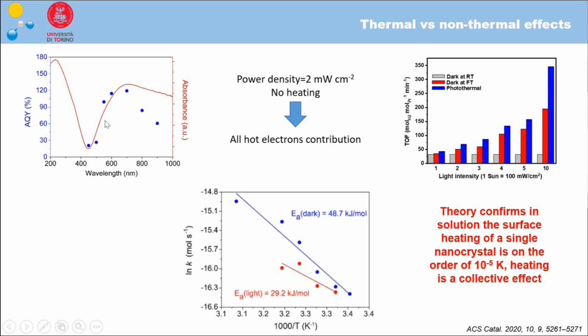You can see that we have an apparent quantum yield which is above 100%. So this, if you are familiar with photocatalysis, can be quite a strange result. Usually when you use a semiconductor, you can have a maximum of 100% quantum yield, because with one photon you generate one electron and one hole. However, there are some semiconductors which can produce more than one carrier per photon. And in the case of plasmonic materials, we have to remember that with one photon we excite a collective motion of electrons. So we have many carriers which are excited and produced at the same time when the photon strikes the material. There are also reports in the literature with 700 or 800% quantum yield. So it's quite an interesting effect of these materials.